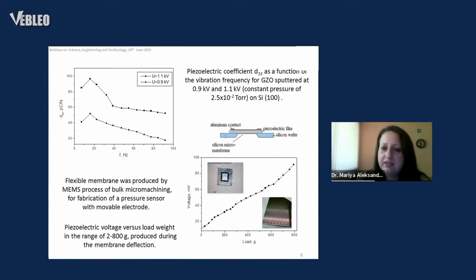Our device is fabricated by a conventional microelectromechanical system, bulk micromachining process. It means deep anisotropic chemical etching of the silicon wafer, and in a specific region, this inner square here in this image, which is 1 millimeter by 1 millimeter, it becomes thinner and its Young modulus is changed. So it is transferred from a solid, rigid substrate to flexible, only locally here. Then this flexible micromembrane is coated with piezoelectric coating. This is the way of transferring mechanical loading on the piezoelectric film,